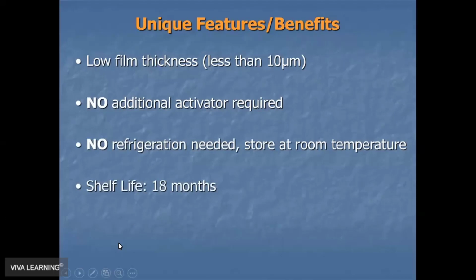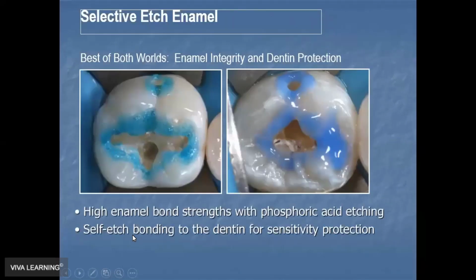What is the shelf life? Is it marked? Shelf life for FuturaBond Universal is 18 months. Now, as we wrap up the adhesion, I'm an advocate of selective etching, where phosphoric acid is indeed placed on the cavosurface margin, radius bevels, etc. And then I'm an advocate of using a self-etcher on the dentin and not having phosphoric acid on the dentin. You can do what you want.